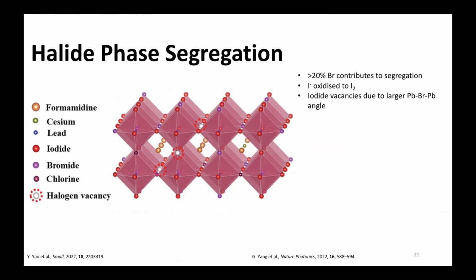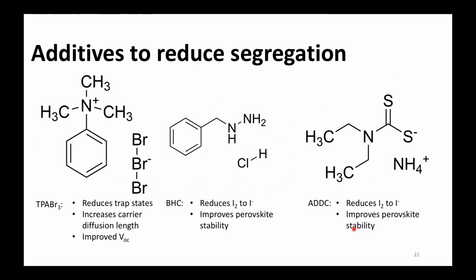You also get vacancies. If you have strain in the material, an ion is kicked out. Here, there are lots of vacancies for the iodine. So here, an iodine is just missing. And you can prevent that with additives, adding molecules that can improve it by using certain tricks. For instance, if I2 is formed, it helps to reduce it back to I-. You can imagine that it can interact with lead. This is also an additive that is used to do the same trick.